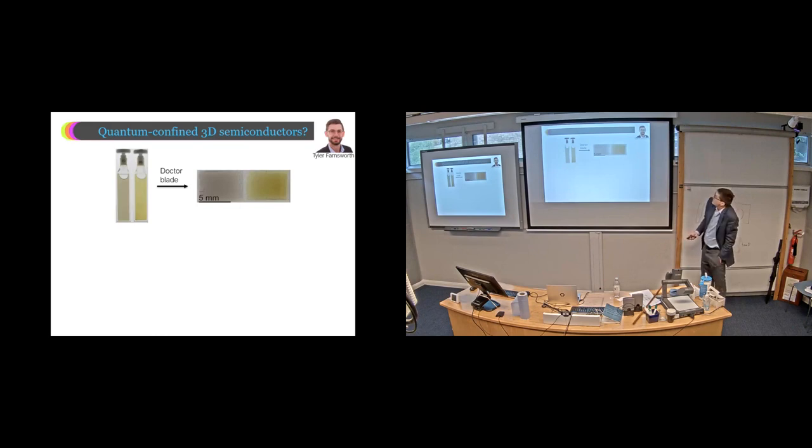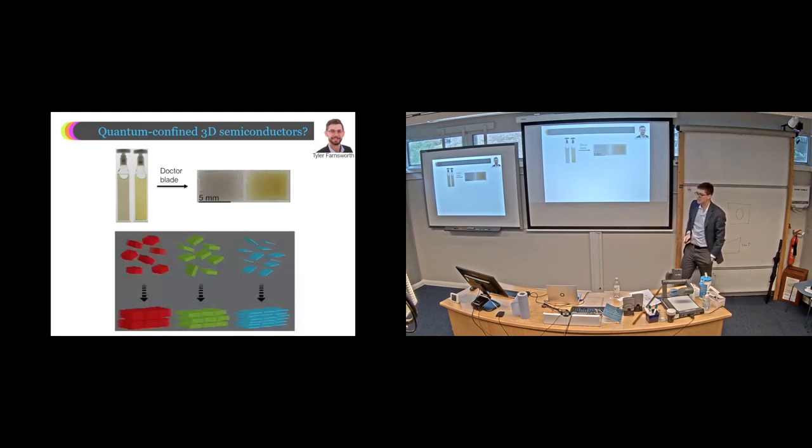But that was kind of our start. We have this really interesting quantum confined building block. We did a really simple experiment. Tyler took these solutions and just doctor bladed films of them. So creating these thick films that are optically transparent and we can see the color. And you can obviously tell that the yellow film came from the yellow solution. And when my students showed me that result, I said, no, that can't be right. Because we're re-stacking the material. And so as you stack these materials back together, they should lose their quantum confinement. But at least according to this picture, that's not what's happening. So there was something going on that we didn't understand and we wanted to understand that a little bit better.